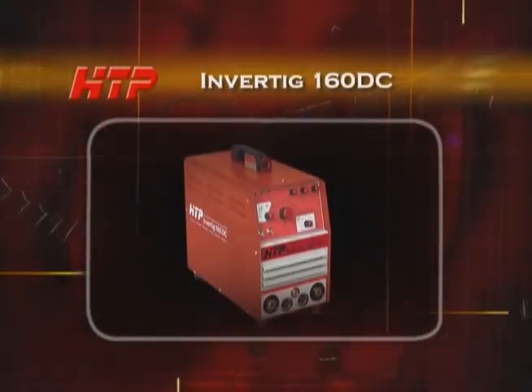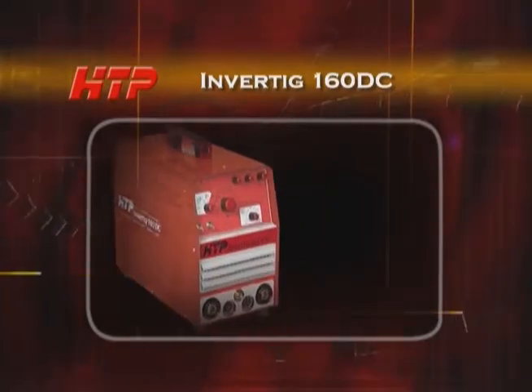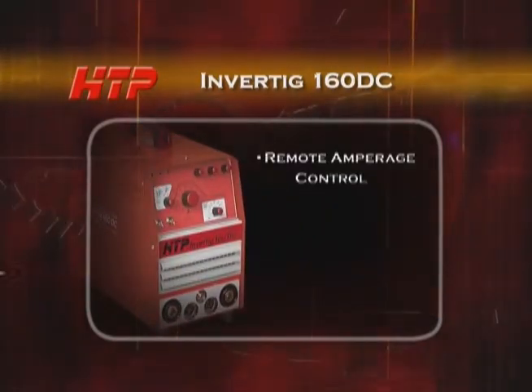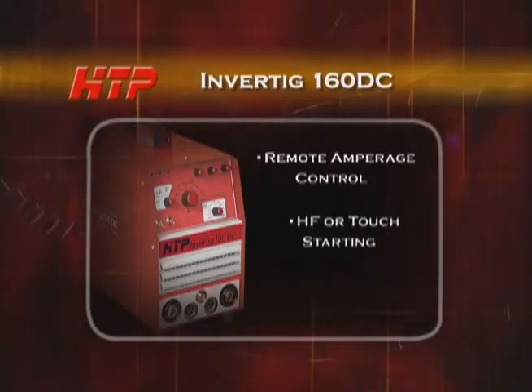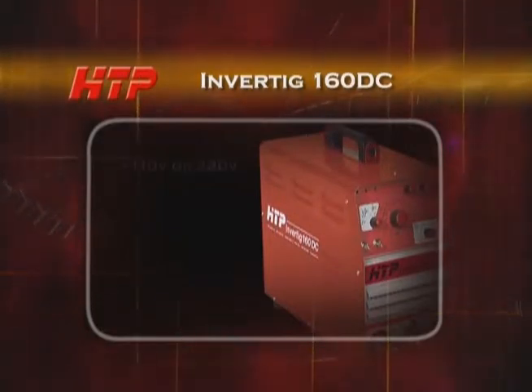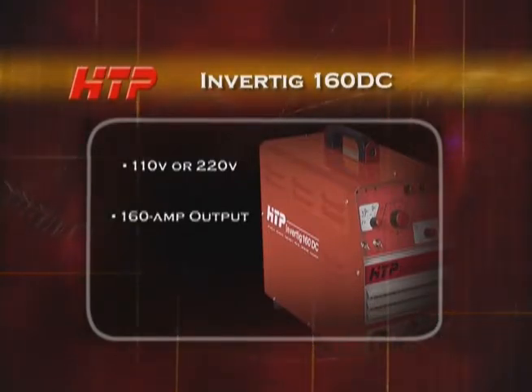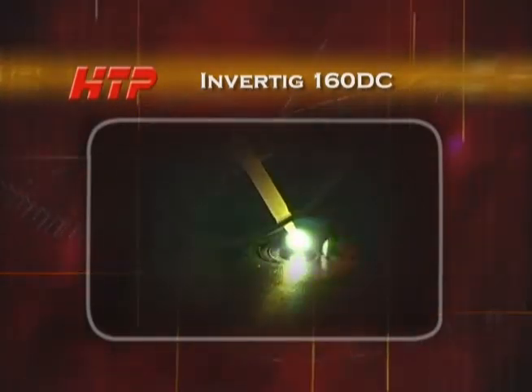The InverTIG 160 DC is a full-featured DC TIG welder. The 160 DC has remote amperage control by foot pedal, your choice of HF or touch starting, and a gas solenoid valve to control the shield gas. It also features the ability to operate on 110 or 220 volts, has a 160 amp output, so you can weld 1/4 to 5/16 inch steel, and a pulse feature to minimize heat input in thin gauge materials.